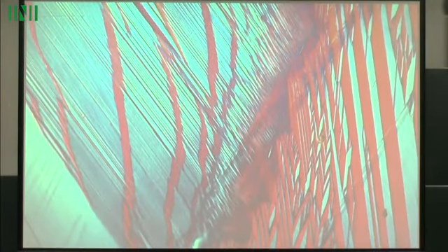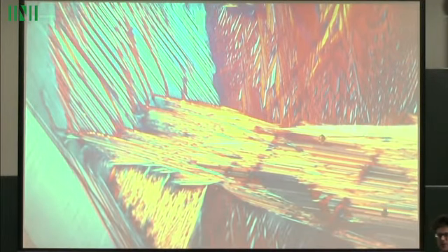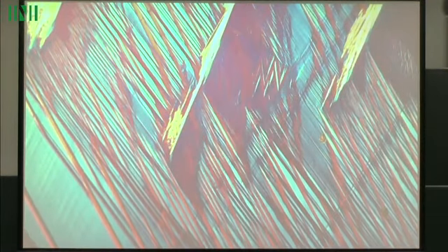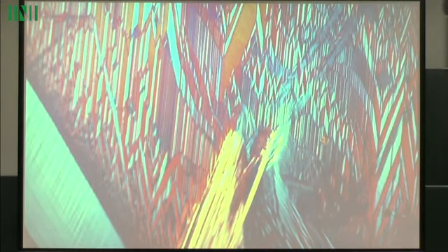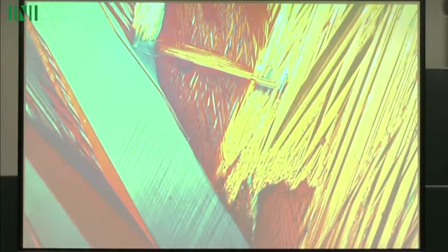So we have the high temperature phase. When we see all blue, that is the austenite phase, then the material is cooled down and we see a microstructure of martensite. Every different color corresponds to a different variant of martensite. And what we see is that by cycling many times, every time we see a different, completely different microstructure. So the problem is mathematically extremely ill-posed, because whatever type of model you try to introduce to predict the microstructures, there's no possibility to have any stability or uniqueness result for the microstructures, because this is not what we observe experimentally.